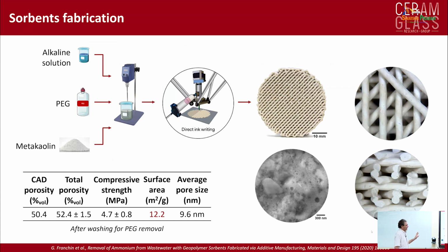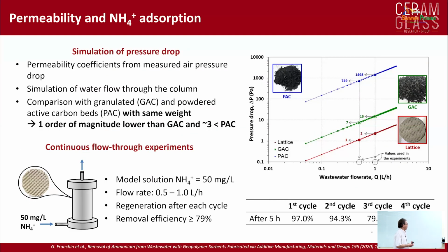So when we started this work and we were trying to use geopolymer as an active material for absorbing cations by ion exchange from water to eliminate pollutants from water, we realized that using PEG was a good approach for fabricating structures with the geometry that we wanted. But if we looked at the BET, so the specific surface area of such materials, we found that PEG would block the mesopores. So we tried calcinating, we tried washing, but with this approach, we were never able to obtain a very high specific surface area. This is still good enough for some applications, especially if they are based on ion exchange. But of course, we wanted to do better, and I will tell you later how we improved the results.